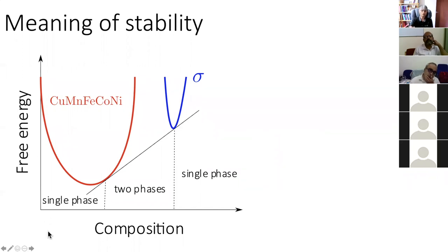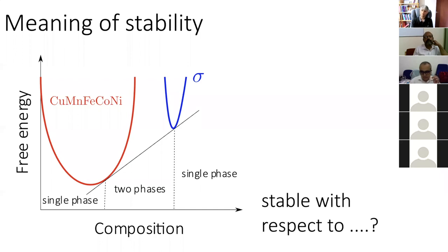diagram, which you are all used to because we plot phase diagrams. We're plotting free energy versus chemical composition in a binary system. I'm assuming here the free energy of this high-entropy alloy, but it could be any phase. And this is another phase. Let's call it sigma. Sigma is usually an intermetallic compound, and I'll come back to that later. But you can see that when we consider stability with respect to another phase, there will be single-phase regions, but also a two-phase region. So we need to think about stability by considering what other phase we are referring to. So always talk about stability with respect to something else. In this case, it's the sigma phase.